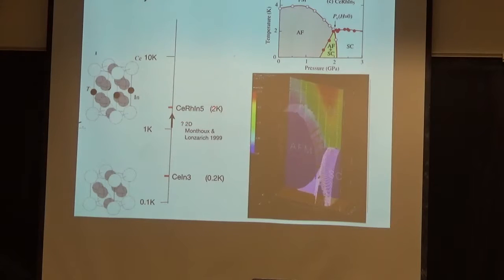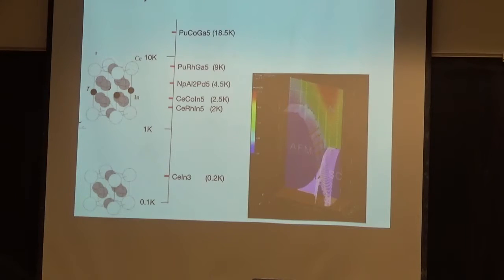But from cerium rhodium indium 5, the question was, well, if you can put pressure on it, then maybe you can do chemical pressure. And if you replace rhodium by something else, such as cobalt, then maybe you'll be able to put that chemical pressure and drive it naturally into a superconductor. And lo and behold, that's what was discovered later. Cerium cobalt indium 5 goes up to 2.5 Kelvin.